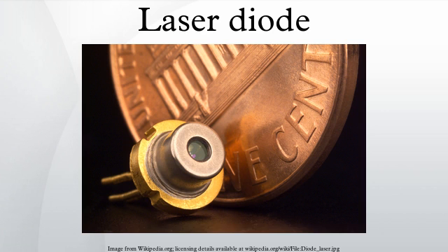The first heterojunction diode lasers were single heterojunction lasers. These lasers utilized aluminum gallium arsenide p-type injectors situated over n-type gallium arsenide layers grown on the substrate by LPE. An admixture of aluminum replaced gallium in the semiconductor crystal and raised the bandgap of the p-type injector over that of the n-type layers beneath. It worked. The 300 K threshold currents went down by 10 times to 10,000 amperes per square centimeter. Unfortunately, this was still not in the needed range and these single heterostructure diode lasers did not function in continuous wave operation at room temperature.